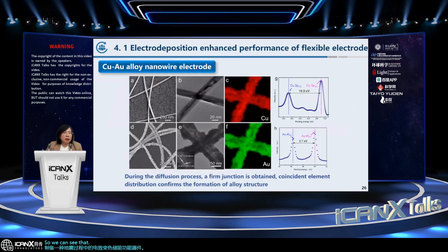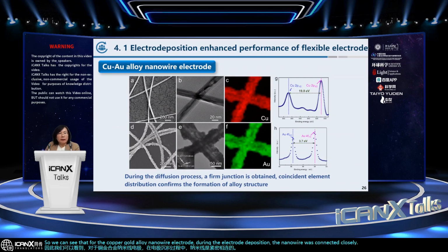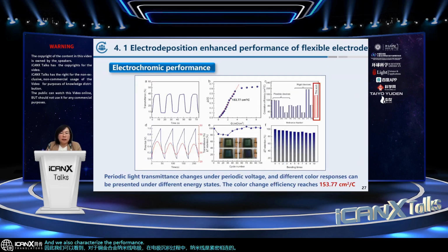So we can see that for the copper-gold alloy nanowire electrode, during the electrodeposition, the nanowires were connected closely. And we also characterized the performance of our electrochromic devices. The light transmittance of the device shows periodic changes under the periodic voltage. And the coloration efficiency of the device can reach about 153. We also compared it with the literature results. We have achieved the same performance as some rigid devices. The device also maintained certain stability in the process of cyclic bending and color change.